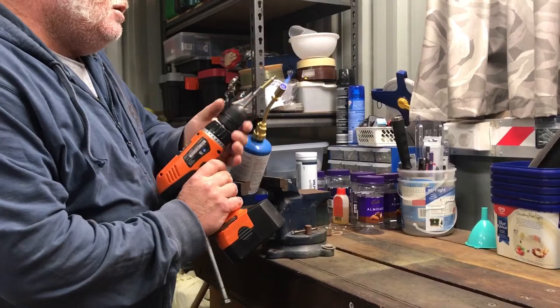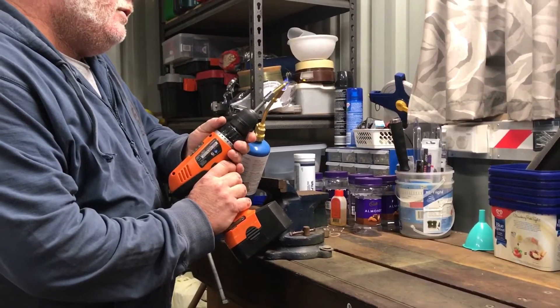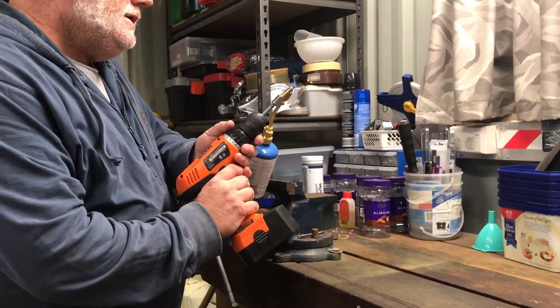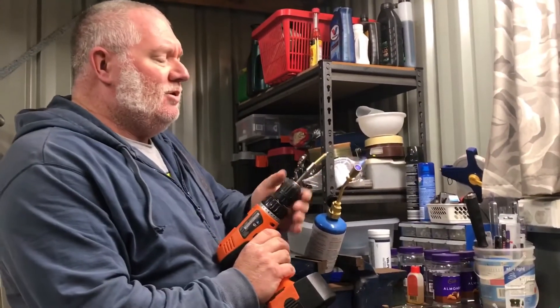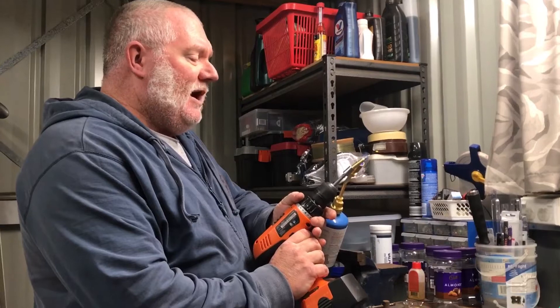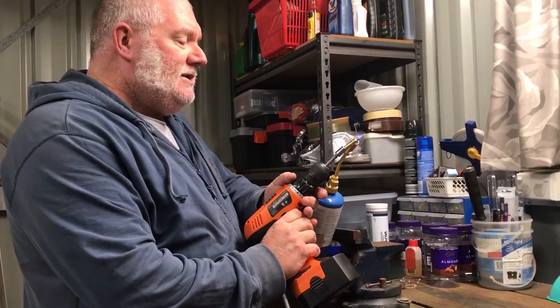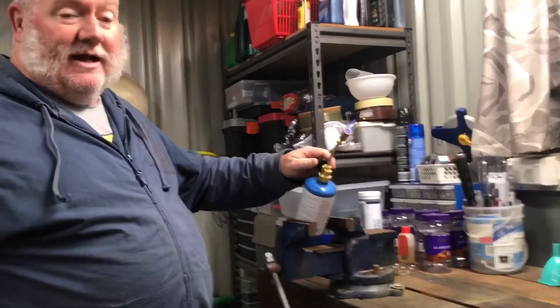Okay, we'll go one more. One, two, three, four, five, six. The neck just starts to discolour — that's pretty right. When the neck just starts to get that little black. You can buy some paste — I can't remember what it's called — and it goes off colour when the thing's done and it's heated up enough. That's enough for that one, and so on and so forth. I think you get the idea.